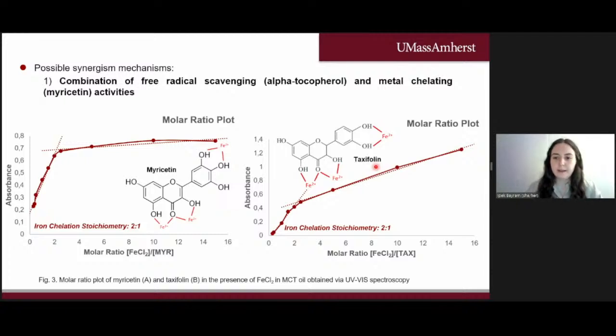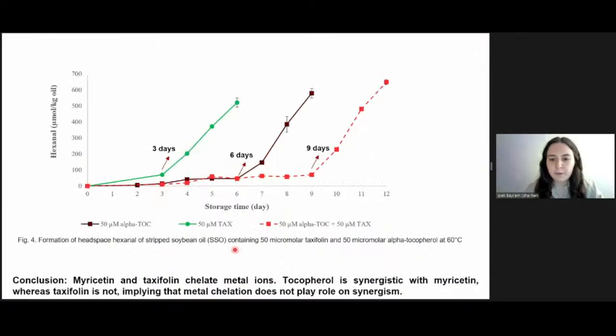Therefore, I designed another oxidation study with the exact same conditions, but this time with taxifolin instead of myricetin. And again, for a 1-to-1 antioxidant ratio, taxifolin had a 3 day lag phase, tocopherol had 6 days, and the combination was 9 days. So they didn't show any synergistic activity together. This concludes that the metal chelating behavior did not play a role in the synergism.